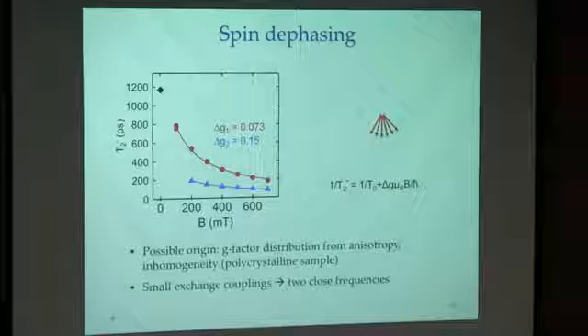OK, we can assume that this pure distribution comes from the G factor, and we can estimate the G factor distribution here for both components. And the G factor distribution, we thought it comes from the crystal anisotropy. So the G factor along the C-axis is different from the A and B axes.